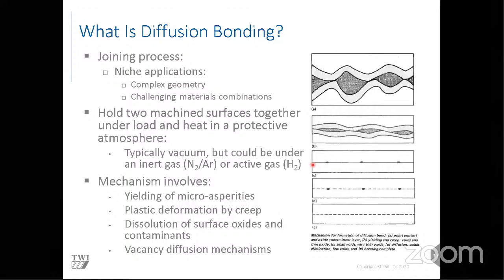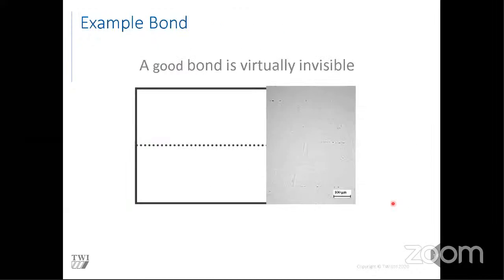Finally, at the end, with the surface oxides, the vacancy diffusion mechanisms begin to take over, and the small pores we've got get smaller and smaller until, if you've got the parameters correct, the diffusion bonded joint is almost impossible to resolve. So I'll give an example on the next slide.